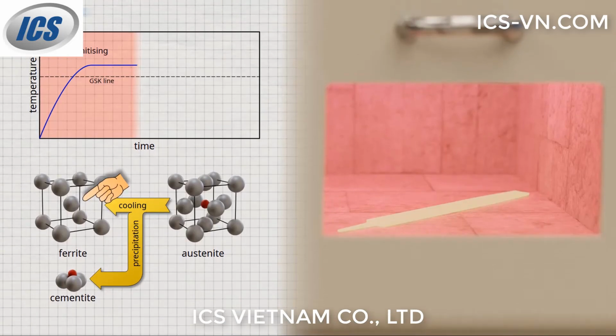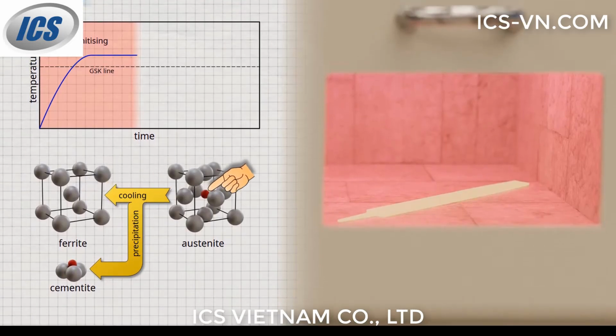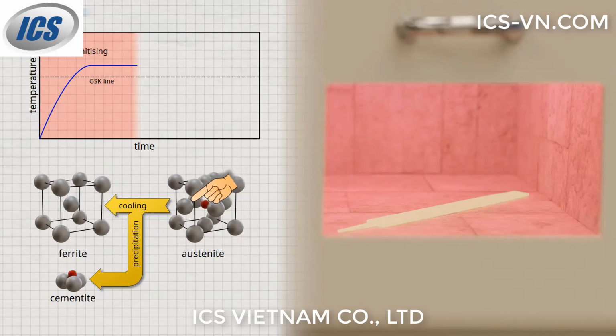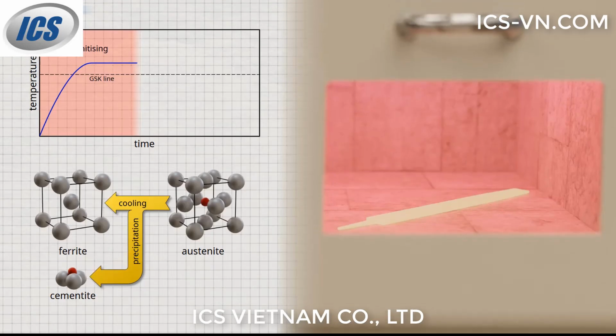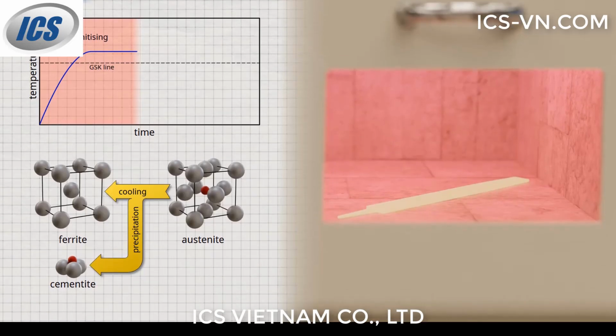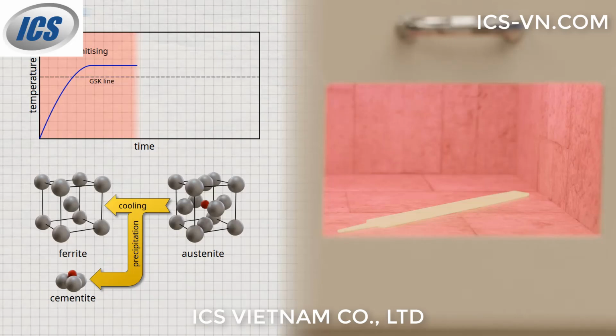Due to the relatively slow cooling, however, the carbon atoms would again have enough time to diffuse out of the transforming austenite lattice and form cementite. Slow cooling from the austenitic state would only restore the original microstructure. The desired microstructural change would not occur.